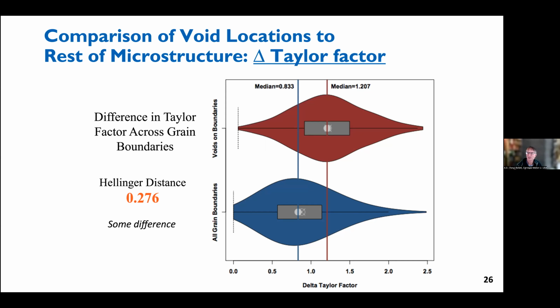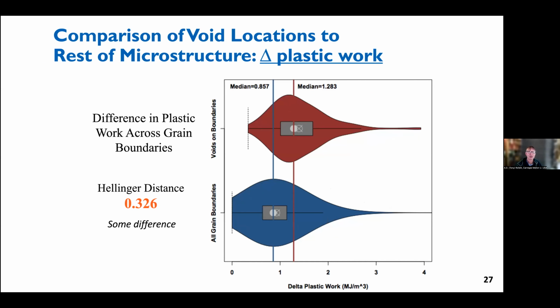It's suggestive at this level, but it's by no means a slam dunk. And you'll just have to trust me that it's the only indicator that we could find that would do this. Now, you can look at a more detailed quantity, plastic work. That's a bit more akin to integrating the work done during the actual plastic deformation, which is not a large amount of strain, plastic strain, non-recoverable strain, but it's certainly non-trivial. And that showed a slightly larger separation in the two distributions.